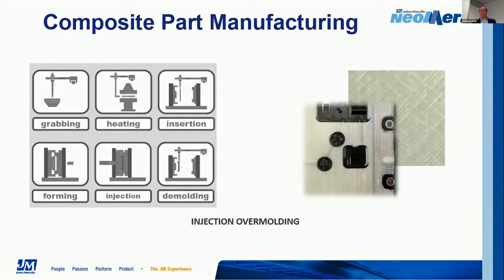And I think Organosheets, injection overmolded will really enable that. And we've seen a number of opportunities there. So in that case, you take your Organosheet, it's heated, goes inside a mold that has this preformed to whatever shape, and then you injection mold around it, and then you pull it out of the mold. And so, you know, injection molding is a very well-known process out there. So the addition of an Organosheet in that process is not a very difficult next step, and it really then enables that injection molded part to be a structural injection molded part.